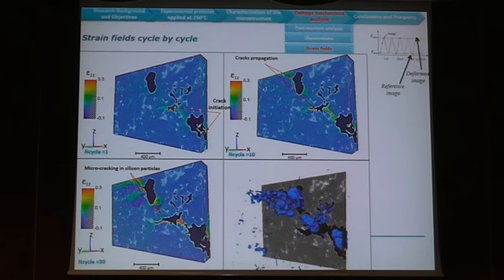Now, if you look at the strain field analysis, here is the strain field cycle by cycle. At the first cycle, after 10 cycles, and after 30 cycles, just before the final failure. Here you see that the strain localization corresponds to the crack initiation, and then here you see the strain localization between large pores, which corresponds to propagation, and here all the microcracks between the pores. If you look at this image at the end, this in blue represents the pore in the reference image before any loading, and behind it is the microstructure just before the failure. So you see well that these two pores are now connected. So there is indeed a coalescence of all the microcracks at high temperature.